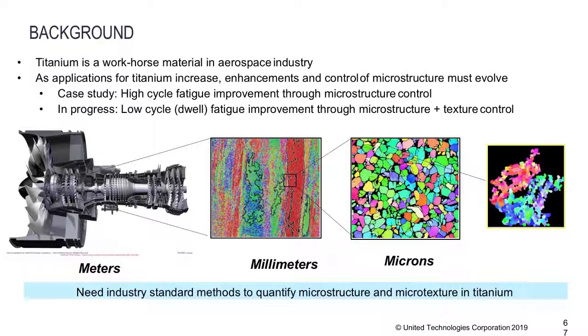For microtexture, they call it cold dwell fatigue because we're in the front of the engine, below maybe 400 or 500 degrees F. That's the regime in which this mechanism is active. So it's our fan blades, our fan hubs, critical parts that if they fail during service, the airplanes can be coming down. So it's a critical life-limiting part for safety.